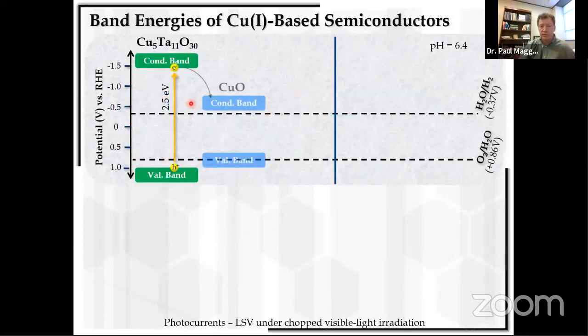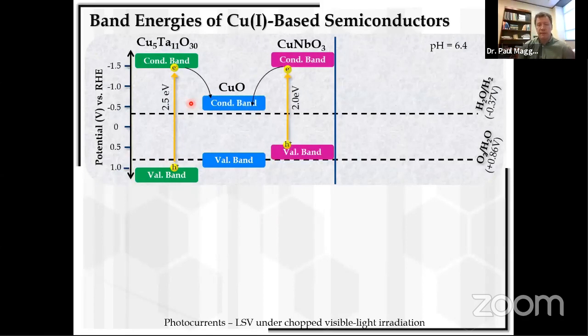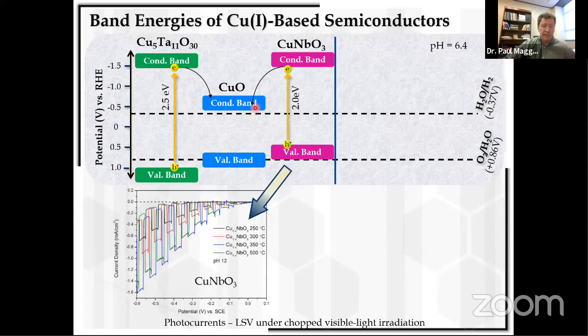Okay, so let me show you the results of the Mott-Schottky measurements and the positions of the bands of each of these semiconductors versus the copper oxide that we know is at the surface. And so the Cu5Ta11O30 phase has a higher band gap. And so there's a large driving force for the electron to move from the conduction band of the Cu5Ta11O30 to those surface islands. And the same thing for the CuNbO3 phase here, copper niobium, which I haven't had time to describe. In both of those cases, we see very high photocurrents for a p-type oxide, such as shown here for the CuNbO3 phase. Very nice.